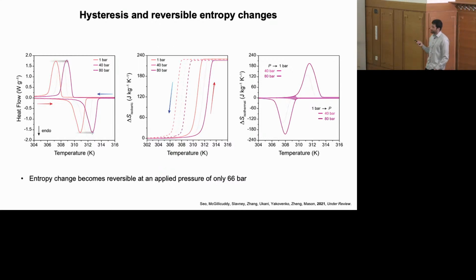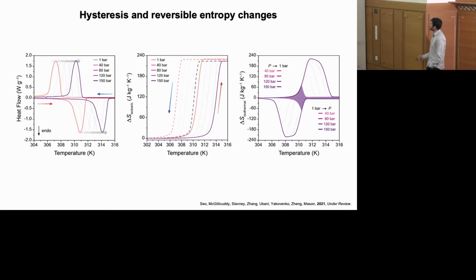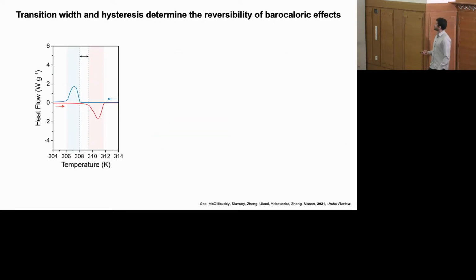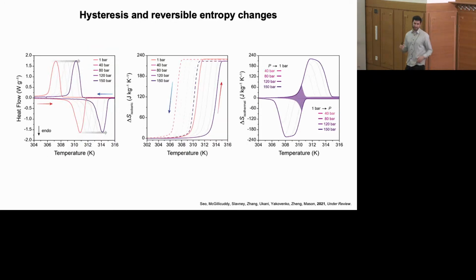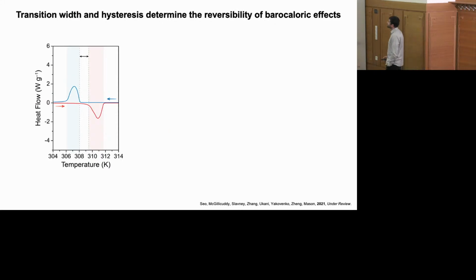If you go to higher pressures, though, then you start to see some overlap between these isothermal entropy curves, and now you can at least partially drive the transition in a reversible fashion. So now you have some hope of being able to actually drive a cooling cycle. And as you get to higher and higher pressures, the region of overlap increases. So this really highlights the importance of driving down hysteresis so that you can operate a cooling cycle at as low a pressure as possible.